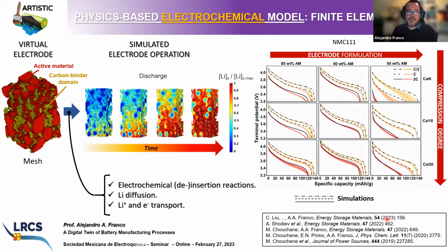And in this paper we are discussing other aspects, such as the influence of this calendering degree or compression degree on the contact resistance between the electrode and the current collector, which plays also a role in the trend that we are reporting here, on the influence of C rate, formulation, and calendering degree on the galvanostatic discharge curve.